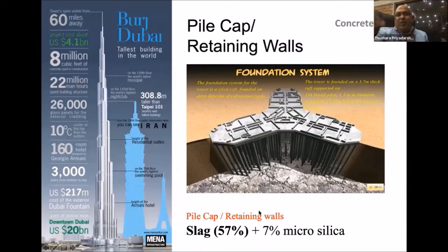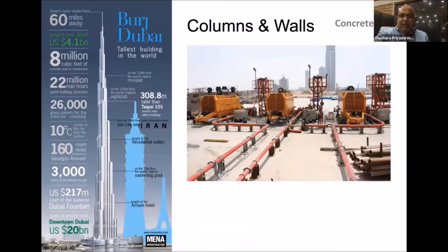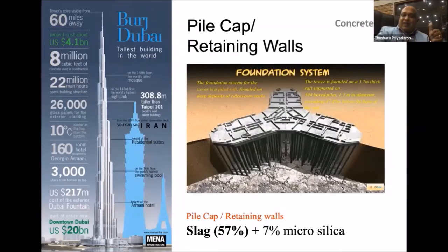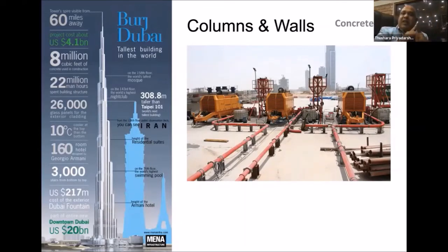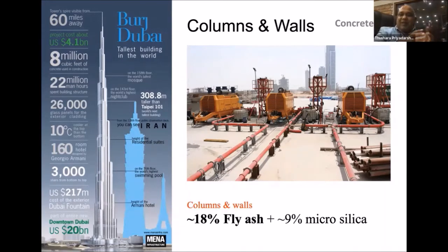So if I remind you once again, I'll show you the complete mix design later. Okay, we start from the pile. It's around 23% fly ash, 7% microsilica. Then we went to the pile cap. Then it was 57% slag, 7% microsilica. Now we have walls. Here we need more strength. This is the difference actually. Now you have to differentiate what you want, because for the pile you don't want that much strength. For the pile cap you don't want that much strength, but for the column you probably need the highest strength for your building. So here you should not take fly ash to a very high level like 25% or 35%. It's better to be at a 15, 18% level, then 9% microsilica. You have to add more microsilica to get strength.